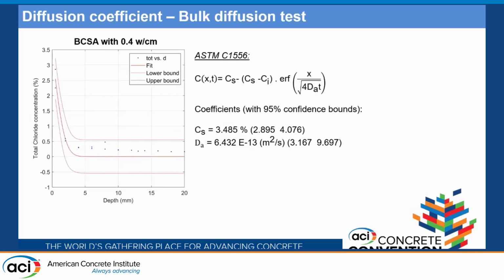Now, I've just shared one of the plots for the diffusion coefficient. I've used MATLAB to calculate the values of diffusion coefficient and surface chloride concentration. And you can see in this plot of total chloride concentration and depth how the pattern looks. For the first top surface it is very high, and then it drops down and it's almost constant across the entire depth.